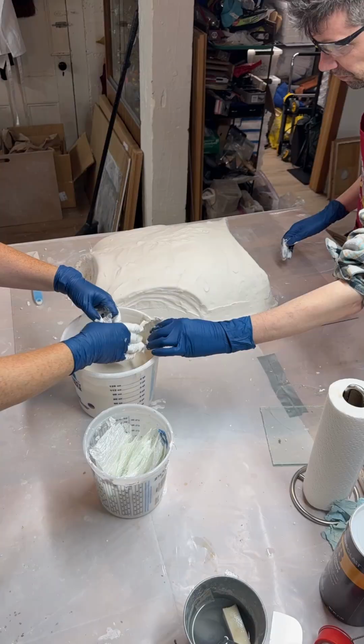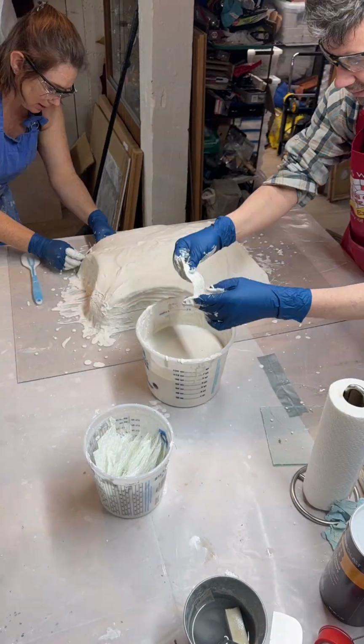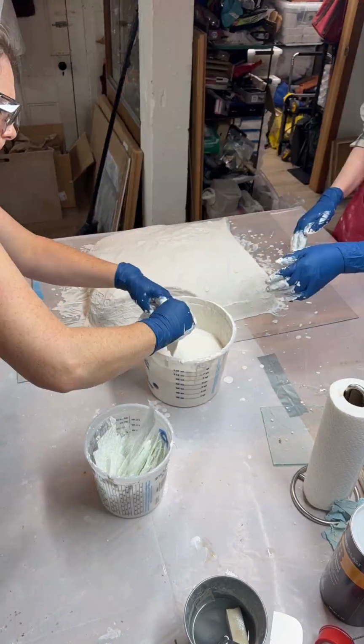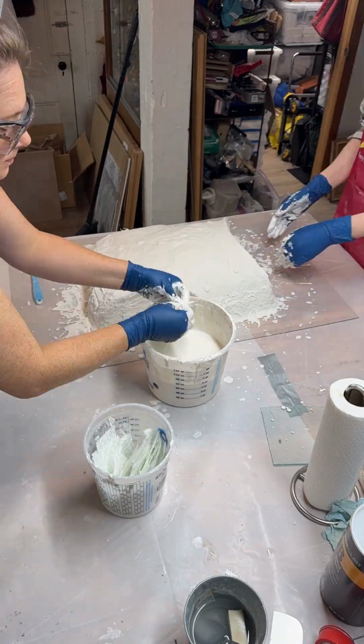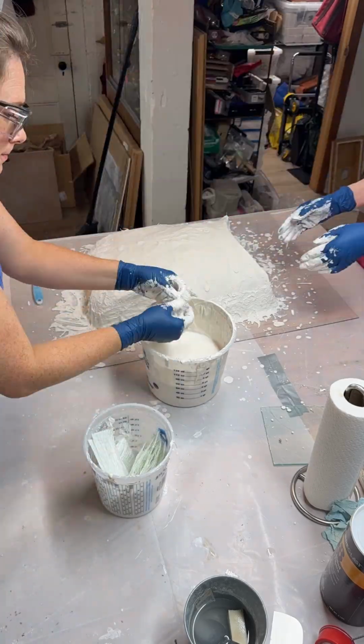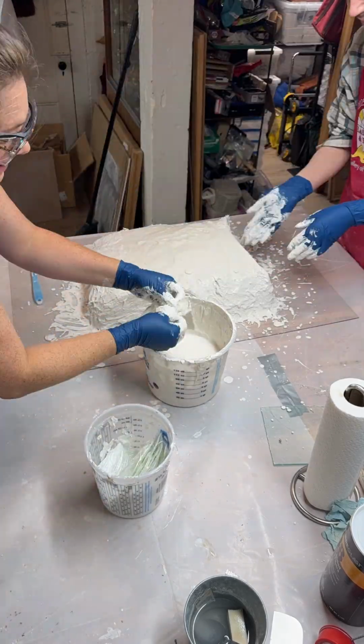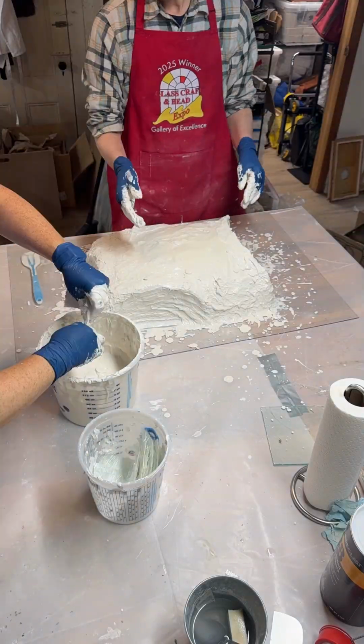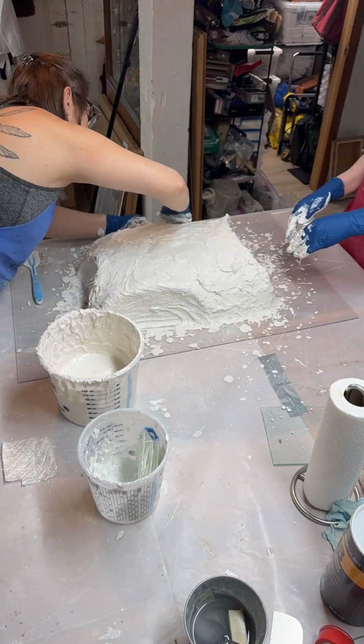Because the back plate is so large and the plaster goes off so quickly, I had to call Andrew in to help with the second mold layer. Again, this is the 50-50 mix of potter's plaster and silica flour, but we're coating strips of chopped fiberglass mat and building them up on the surface for strength.